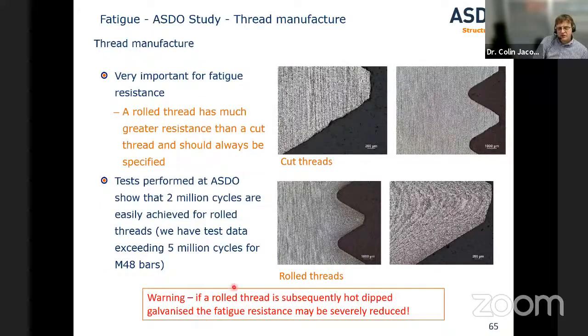And if we're looking at threads, it's very important if you're specifying a threaded tie rod in a fatigue situation that you specify rolled threads. So a rolled thread has a much greater resistance than a cut thread. If you're aware, the two methods of making a thread is generally you can take a steel bar and you can either roll the material, you move material to form the thread, you don't make any cutting, or you cut material away to make the thread.